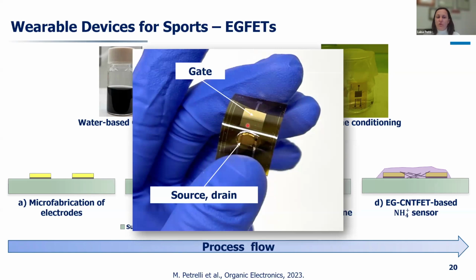So we have this geometry with these big pads, because sometimes we also functionalize the gates. In that case, it is less needed. But you see the interdigitated source and drain contacts and the carbon nanotubes between the contacts. And this is before the electrolyte. The membrane, as you see here, is drop casted, and this now gets a chamber, and the sweat is actually then added in order to connect this whole area.